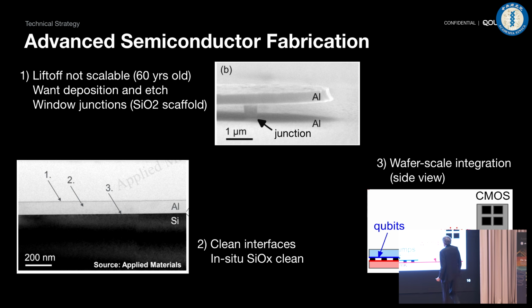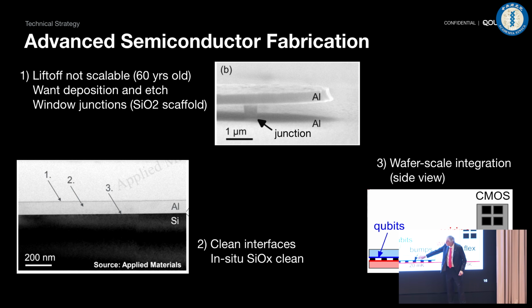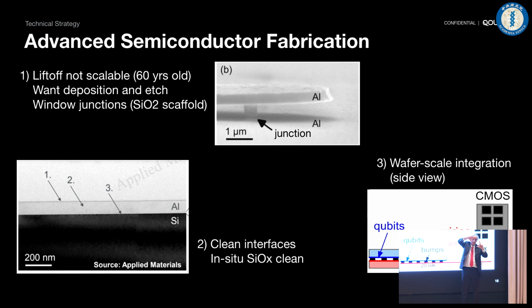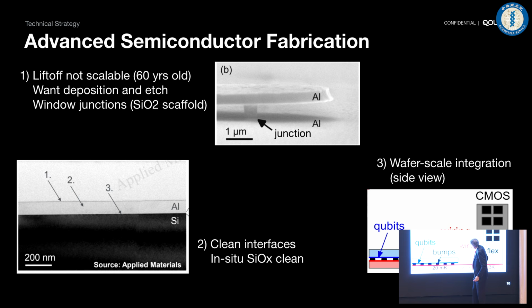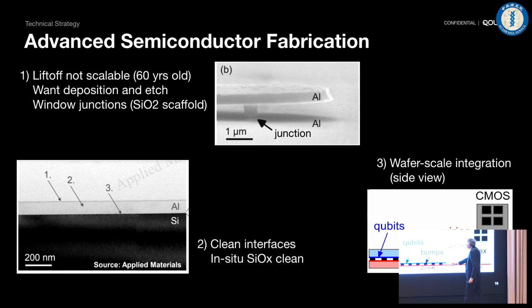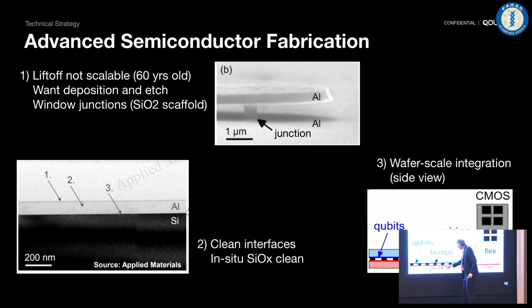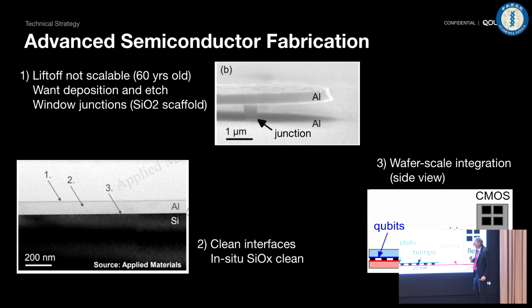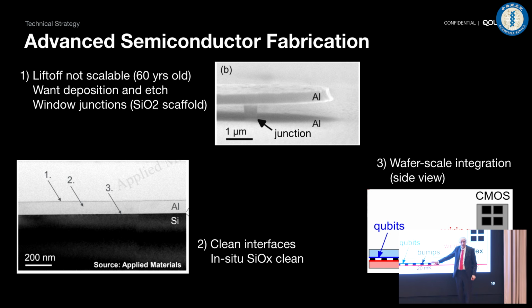What we have here in the blue would be a qubit wafer, maybe about that size, 14 centimeters by 14 centimeters. You then bump bond it to a 300 millimeter wafer, shown in red, about that size. Then the wires from the qubit wafer go through the bump bonds and then go through the silicon wafer. And what's amazing is we have some technology ideas where one end of the silicon wafer can be at very low temperature, the other end at this higher temperature, 3 Kelvin.